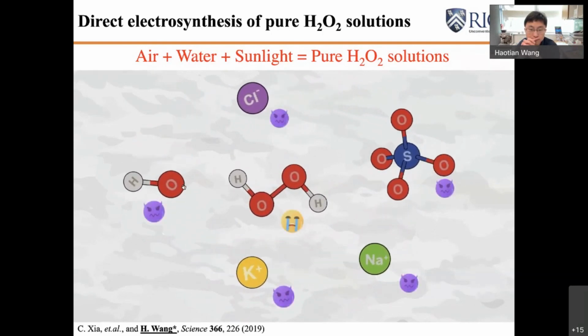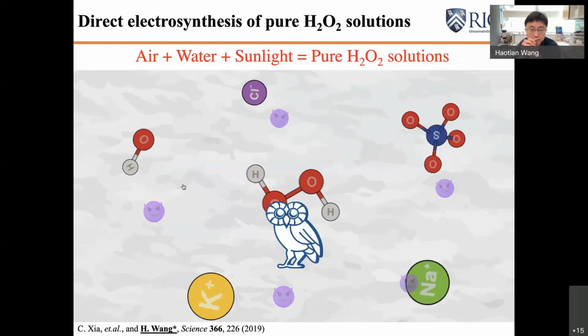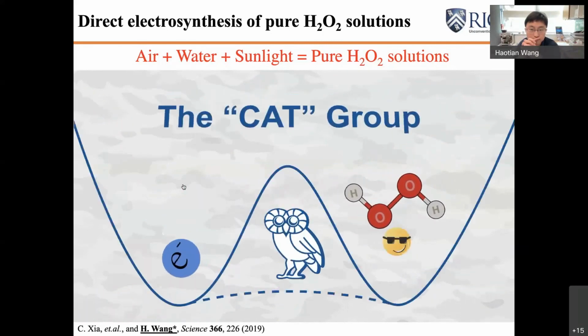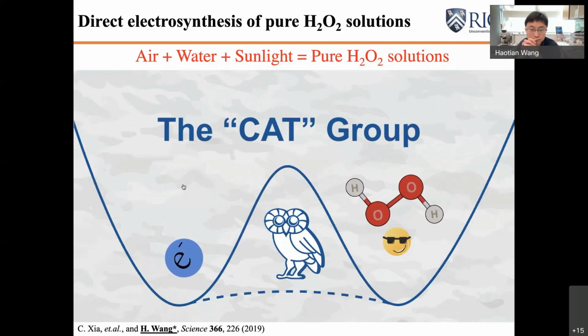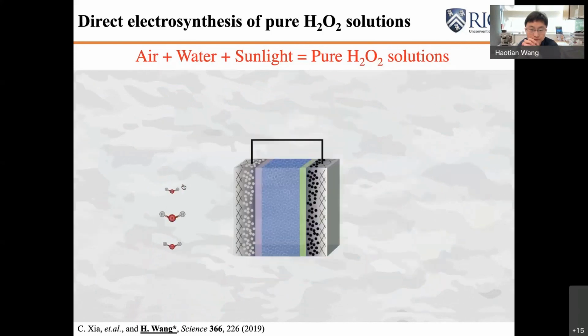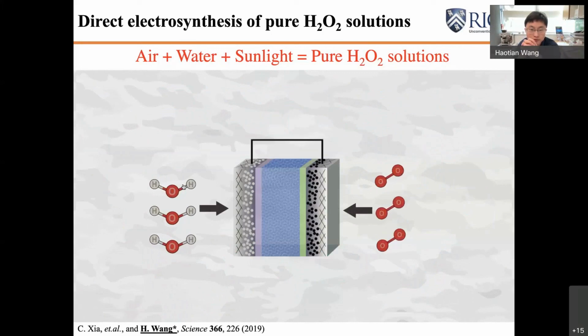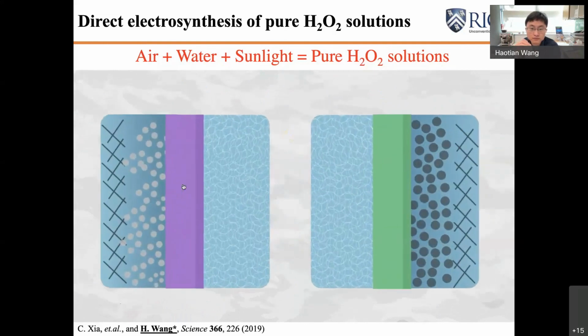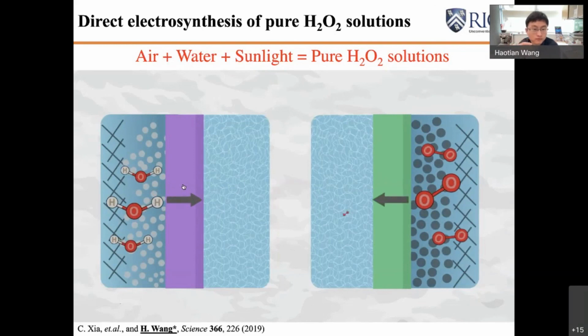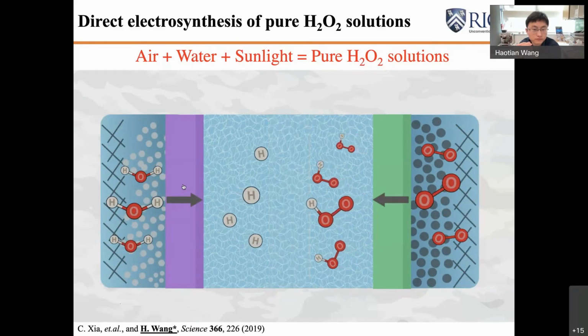Now, the CAT group at Rice University has successfully addressed this challenge by developing an electrolyzer that uses a solid electrolyte to continuously produce hydrogen peroxide solution without involving any impurities. This porous solid electrolyte layer can efficiently transport ions, just as the liquid electrolyte does, but does not dissolve in water so as not to introduce any ionic impurities into the generated products.